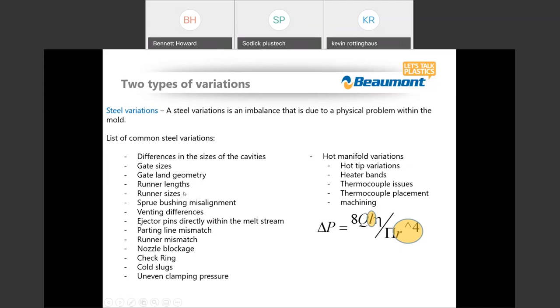Why? Because we're not in the business of molding runners. We're in the business of molding parts. And that can be a problem, because up until the point of ejection and degating, that runner is part of your part. So everything that happens there is going to possibly influence what happens in that very important part. Sprue bushing misalignment, venting differences, ejector pins directly within the melt stream. So we sometimes end up with pins inside of the runner.